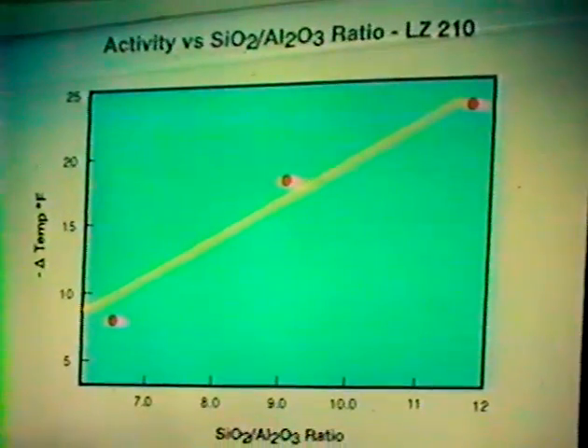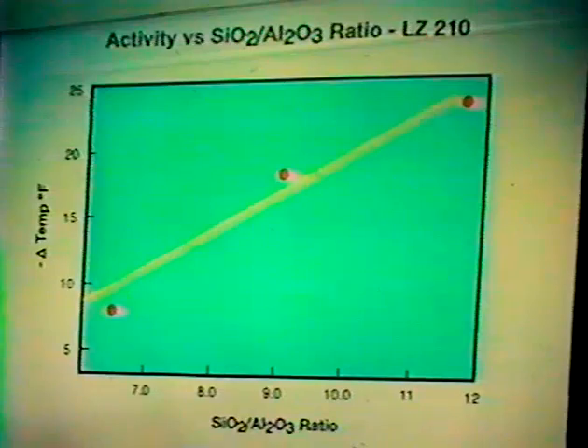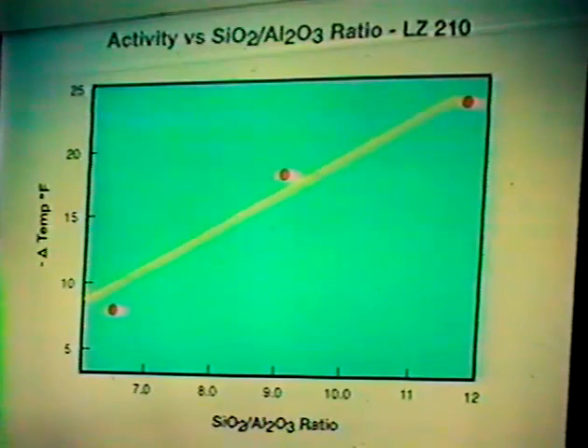So although we're decreasing the amount of alumina in the structure, and therefore probably the number of acid sites, we are effectively increasing the cracking activity by some means which we do not understand. We can also change the silica to alumina ratio by treatment with acid.